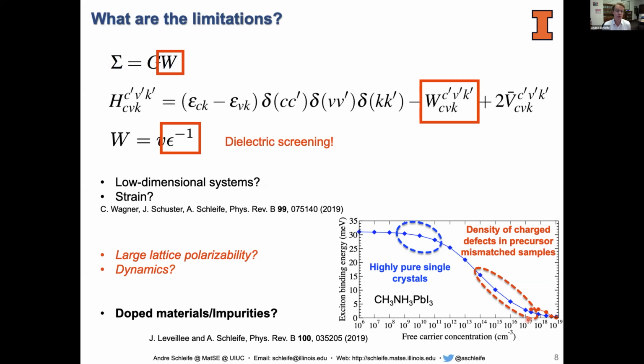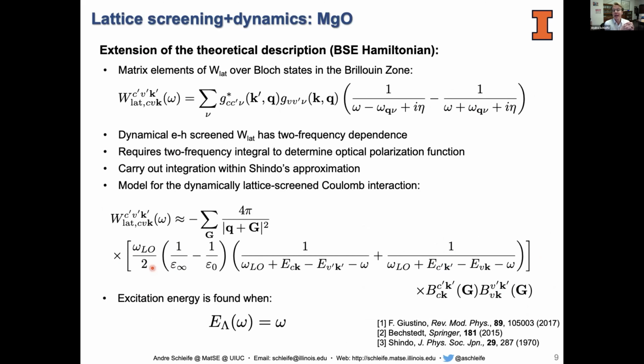Okay, so with that, let me come to this dynamics problem. And I will show you one more slide with equations, which is this one. Earlier I said, typically when you solve this Bethe-Salpeter Hamiltonian, you assume that this screened Coulomb interaction is frequency independent. Now, you can think about examples where that would not be fulfilled, right? One may be electronic screening, like purely effects due to electronic dynamics. That is typically believed to be small simply because the plasmon resonance in a material is typically much higher than the exciton binding energy, and so the remaining dynamics in the low energy range of the exciton binding energies is not so big. But we do believe that in a material with a large lattice polarizability, there could be a contribution due to phonons. So Frank also talked about the electron-phonon interaction. That would be what needs to be taken into account here, right?